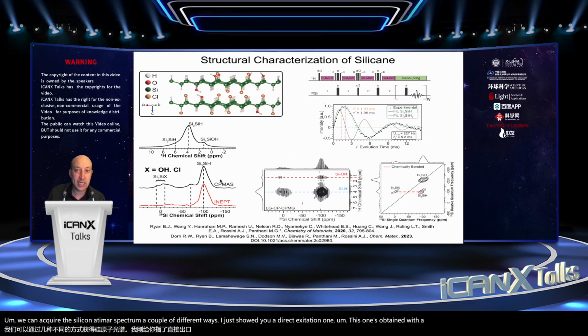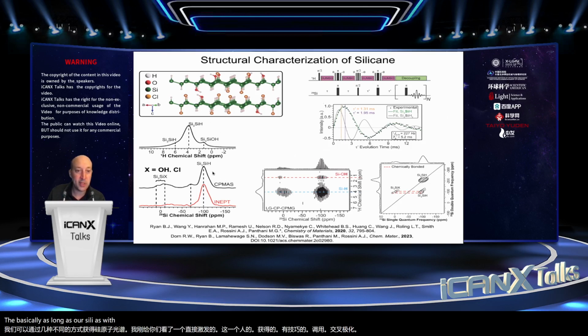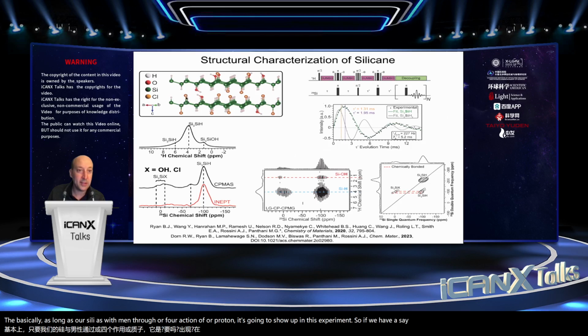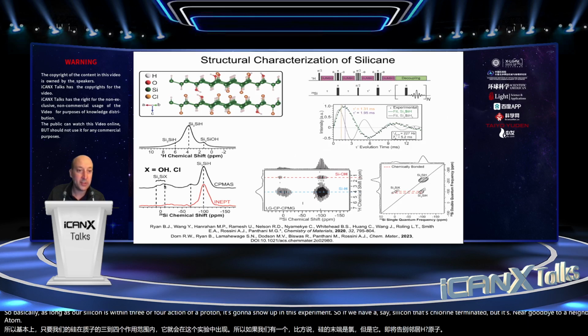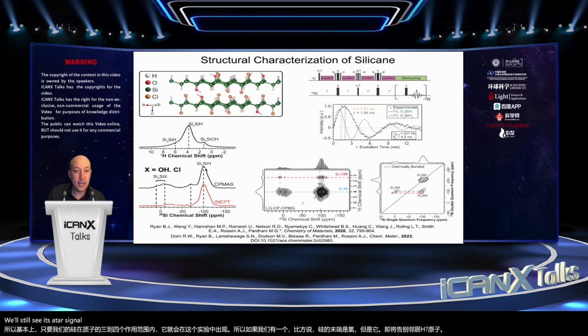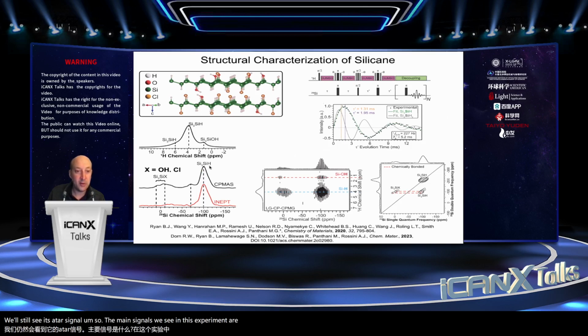We can acquire the silicon NMR spectrum in a couple of different ways. I just showed you a direct excitation one. This one's obtained with a technique called cross-polarization. So basically, as long as our silicon is within 3 or 4 angstroms of a proton, it's going to show up in this experiment. So if we have, say, silicon that's chlorine terminated, but it's nearby to a neighboring H atom, we'll still see its NMR signal. So the main signals we see in this experiment are, again, the ones that we're assigning to H-terminated silicon atoms.